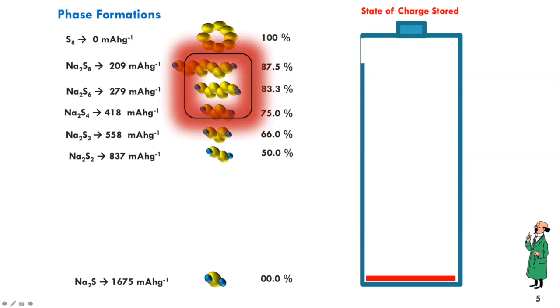If you want to improve the efficiency of the cell, lithium sulfur or sodium sulfur, you can restrict your sulfur to S4. But that is not possible. I have seen a few papers where it was restricted to S4 and then showed very high reversible characteristics. But I am not sure how well that can be explained when you have dynamic situations. Okay, so this is one zone where it is highly reversible.